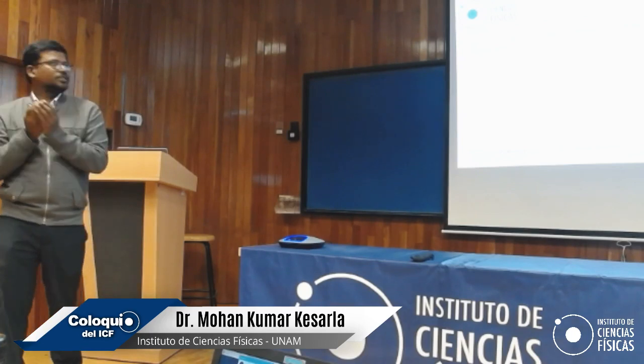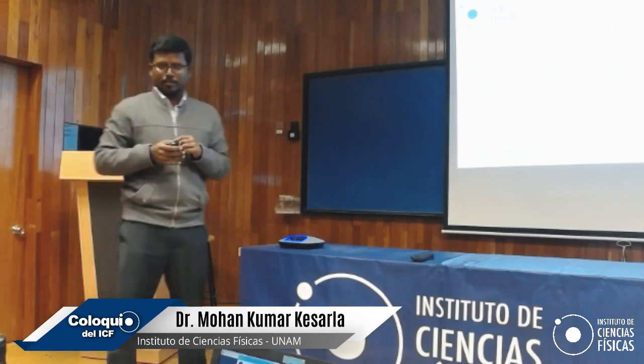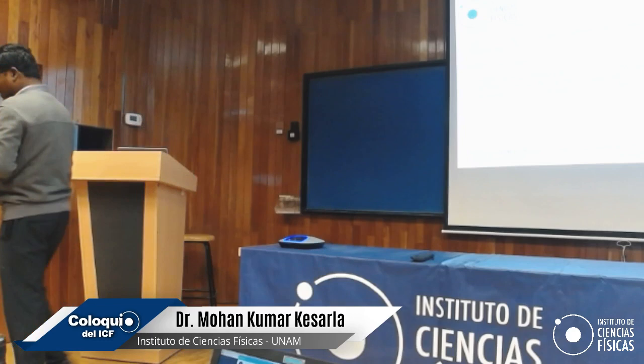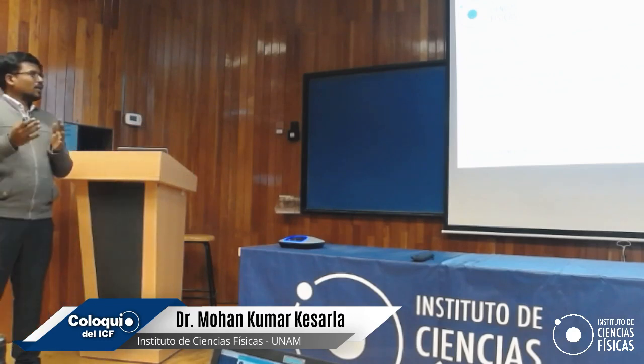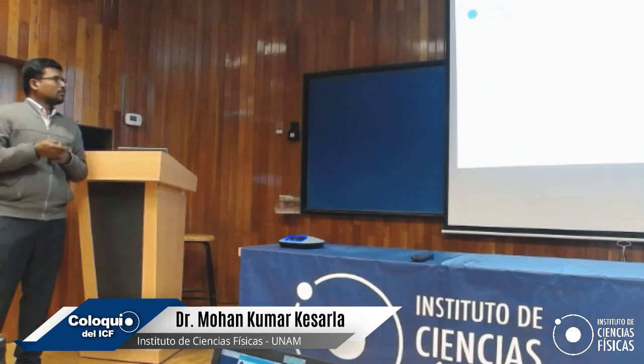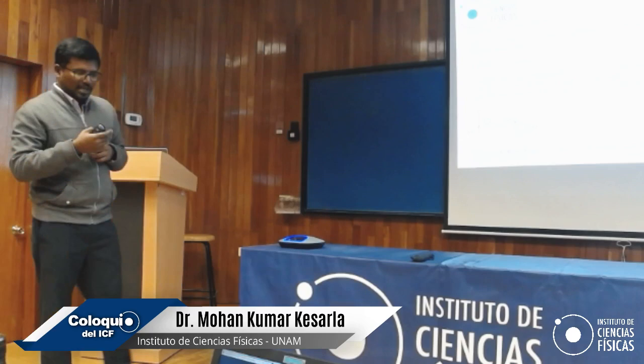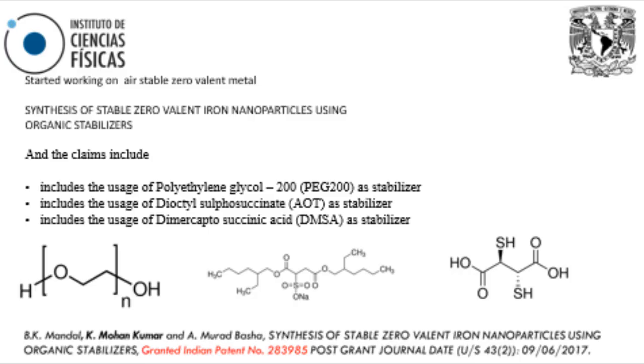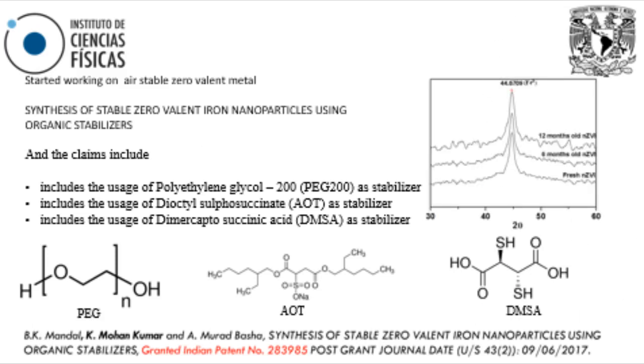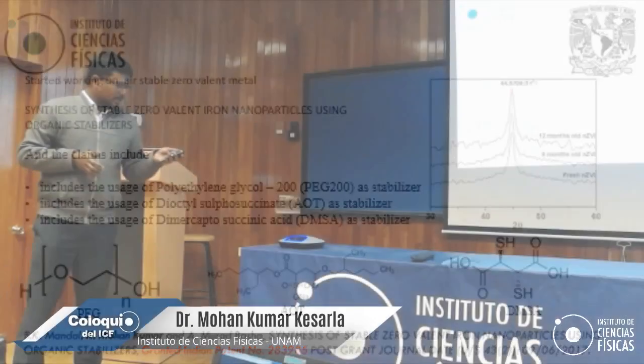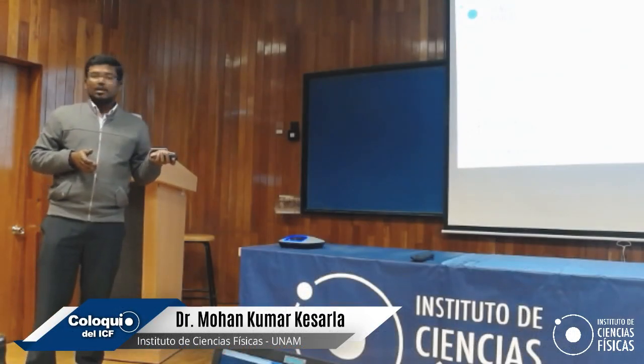In this regard, we tested a lot of polymers, and we used three different ones: polyethylene glycol, sulfosuccinate, and dimercaptosuccinic acid. These three stabilizers protect the zero valent iron. After protecting the zero valent iron, you just take it and put it in the air, and nothing is going to happen to those iron nanoparticles. We stabilized it using these three, and you can check the XRD patterns even after 12 months. There is no change in the zero valent iron, and we didn't see any iron oxide peaks here. So this was actually a patent which was granted recently in 2017 for this work.